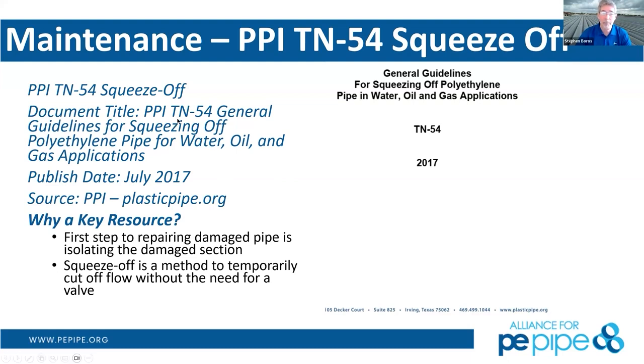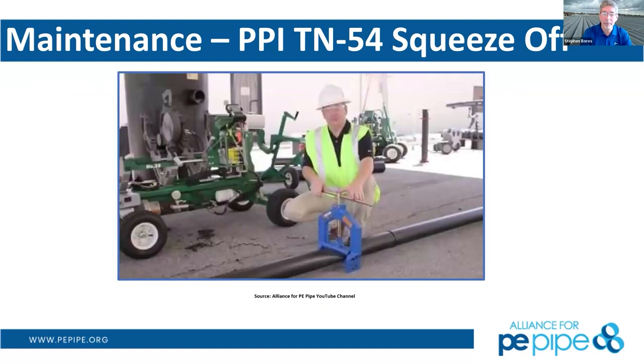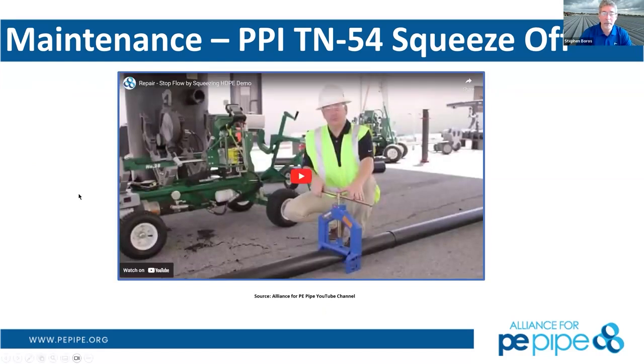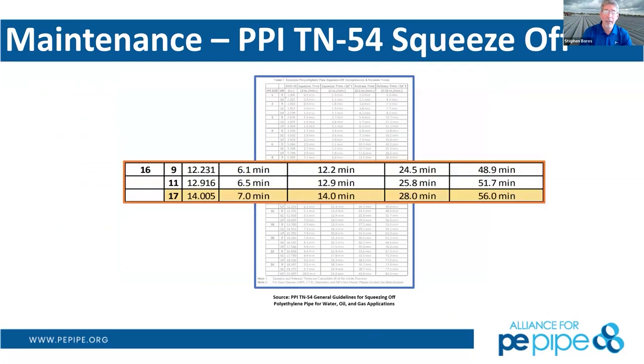And there's a guide for this, PPI TN 54, General Guidelines for Squeeze-Off of Polyethylene Pipe for Water, Oil, and Gas Applications. This is going to be different from gas distribution applications, which has some different caveats in it. But you go through this methodology, and this will make sure the pipe is not damaged. I'm not going to play the video here because it takes a while, but this is essentially what a squeeze-off tool looks like. It's a barred tool, barred on top and bottom with a very specifically designed radius. And then you squeeze off at a very specific squeeze rate, do your repair, and then you release that squeeze again at a very specific rate. That's going to be key in this process.